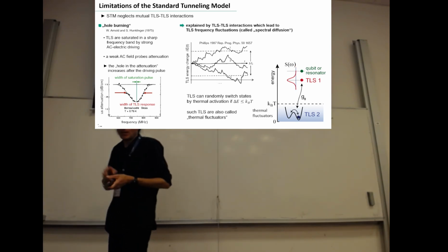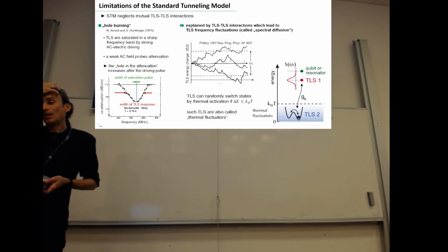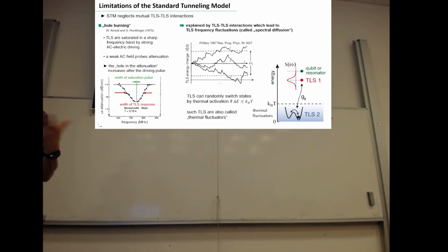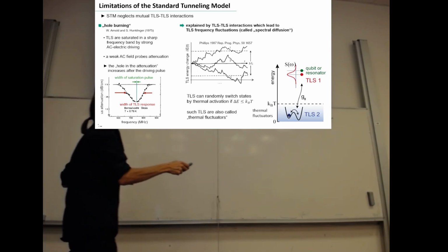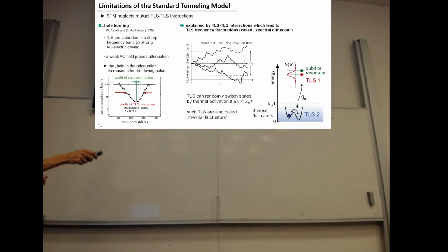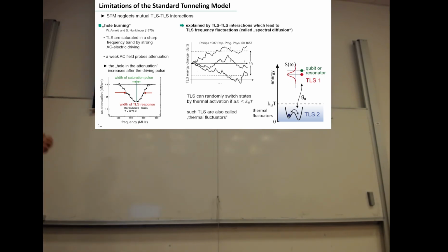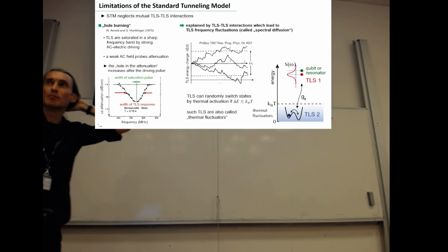Yeah, and this actually also generates big problems when we want to build quantum systems which are free of thermal noise, because even at low temperatures, you will still find very small energy fluctuators, which can then transfer these fluctuations into a higher frequency band, leading to some change of the spectrum of these high frequency defects, which of course can then affect the properties of your quantum device.